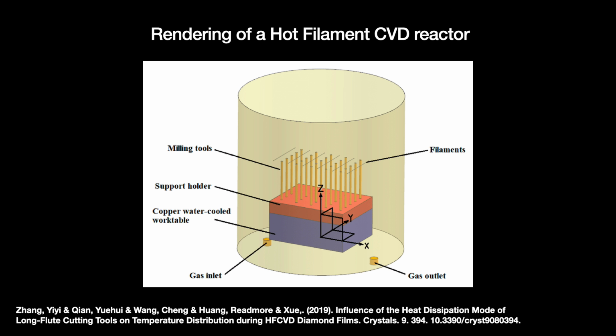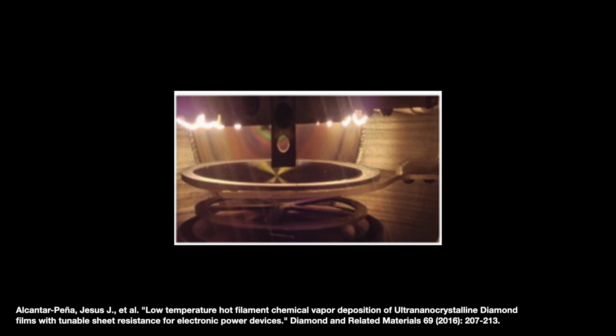Hot filament CVD does work and is a pioneering method, but there were several serious problems. First, while it represented a breakthrough leap in formation speed, it was still initially too slow. The first experiments produced a growth rate of about 1 micrometer per hour, assuming that you wanted a nice gem diamond of 5 millimeters tall, generally about 2 carats. That will take 5,000 hours or 208 days.